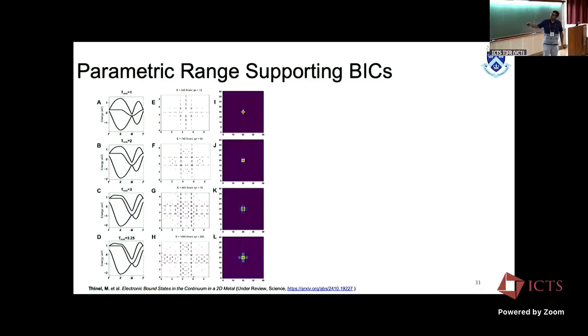So then you can play with tight binding, and we can ask at what point does this whole thing fall apart. And it turns out that you have to modify the hoppings by quite a lot in order to completely delocalize these states. So up to a very reasonable range of hopping parameters, they stay localized. The localization length increases, but they still stay localized. In experiment, they're very localized. We can measure this localization length. It's within 2 lattice constants.